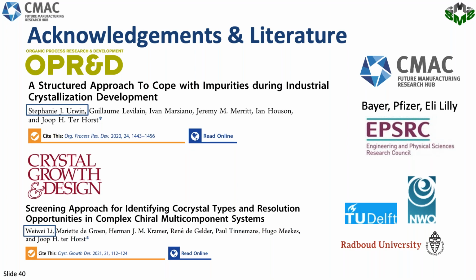You would have to adapt this to, say, the detection limit of the analysis tool. So we performed crystallization experiments in the Crystal16 and the Crystalline, say 0.5 milliliter to about 8 milliliter. That is a nice convenient amount to use. Okay. Another interesting question from Sean Kinnan.